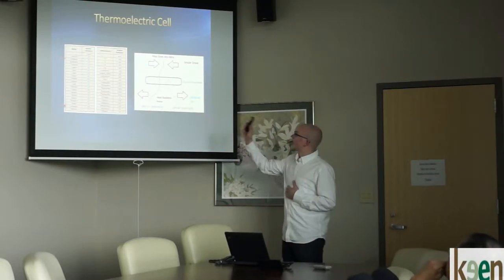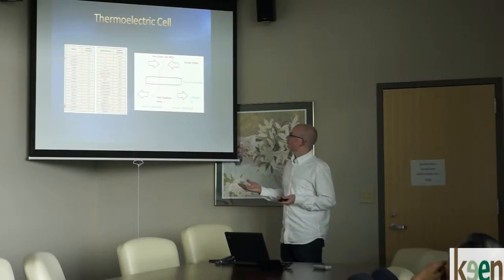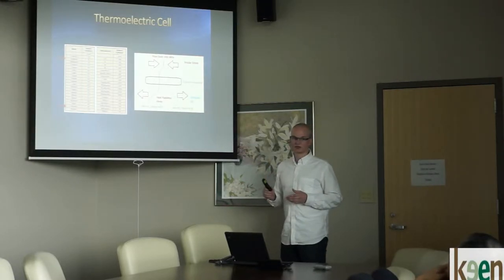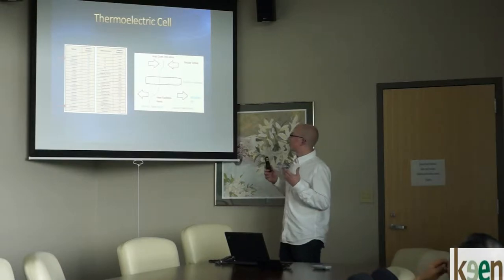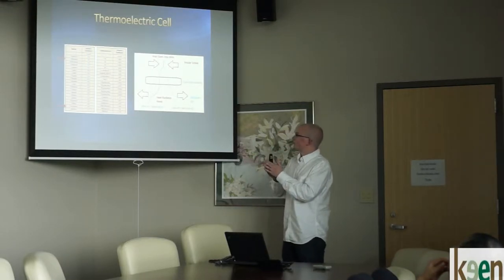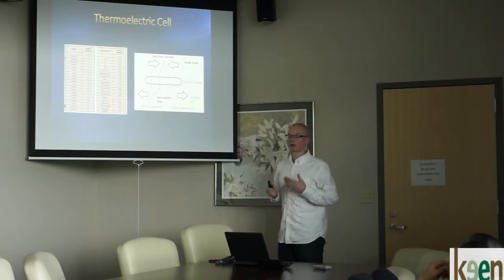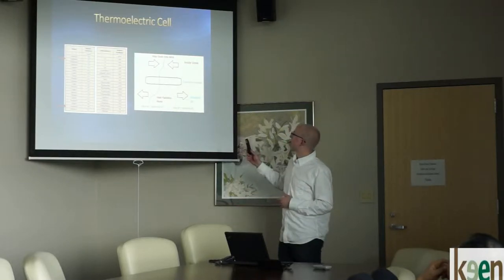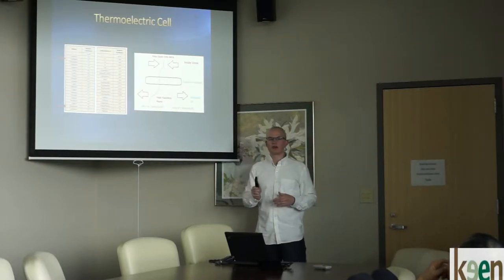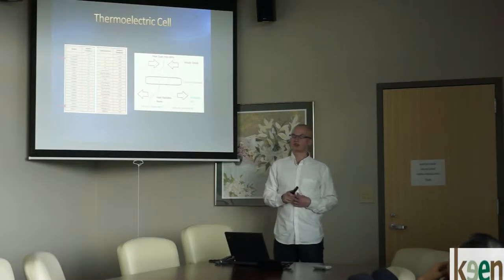The nichrome has a positive Seebeck coefficient. The constantan has a negative Seebeck coefficient. So I theorized that if I made a thermoelectric cell of those two materials, I'd be able to generate a voltage. And so I built one, and it worked. The problem was that it had too high of an impedance for the voltage it got out.